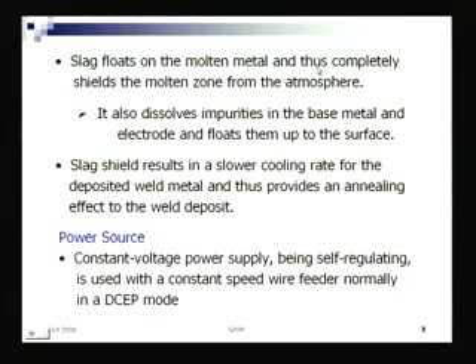Slag floats on the molten metal, right, and thus completely shields the molten zone from the atmosphere, as well as it dissolves impurities of the base metal and the electrode and floats them on the surface. So, any impurity also gets removed. The slag shield results in a slower cooling rate. That is another aspect, because when you are gradually welding, the process goes something like this.